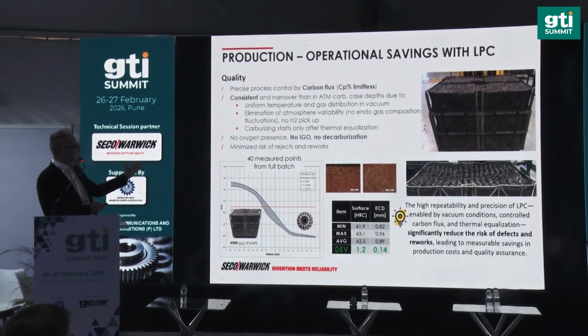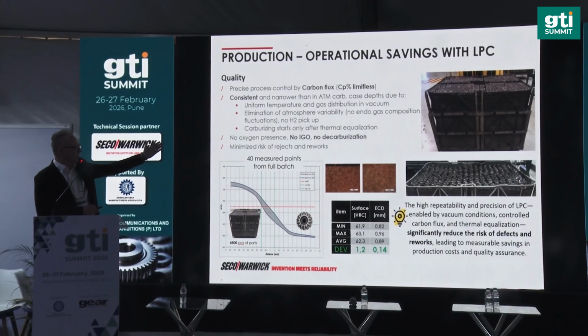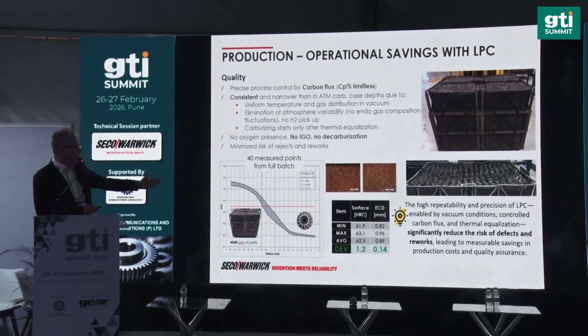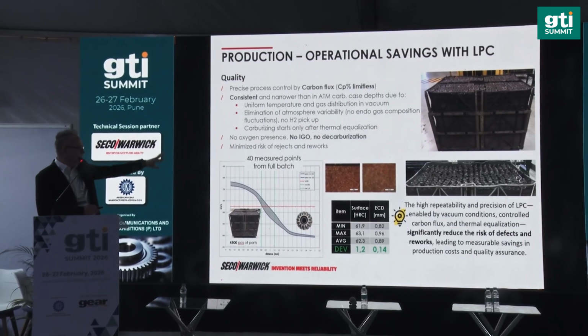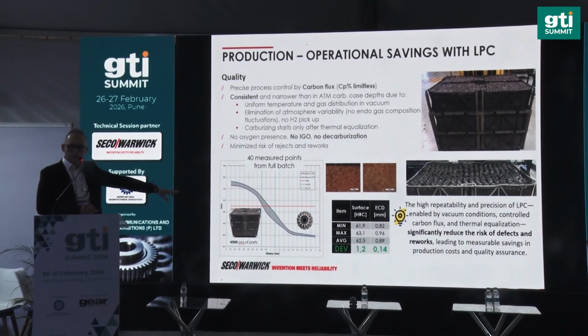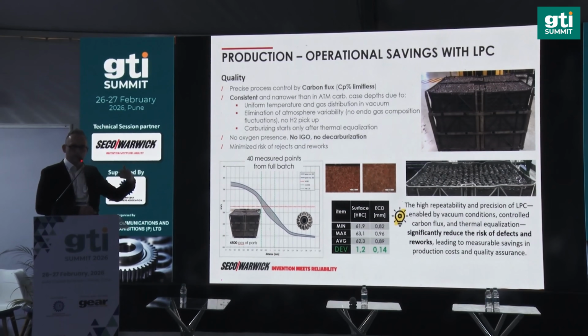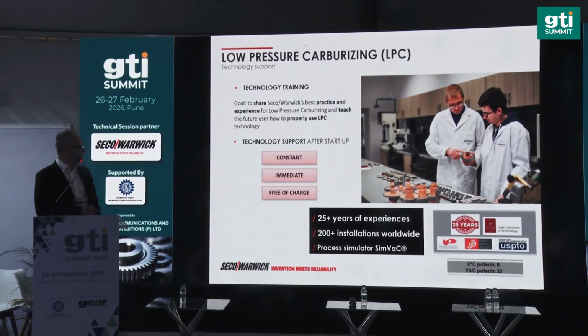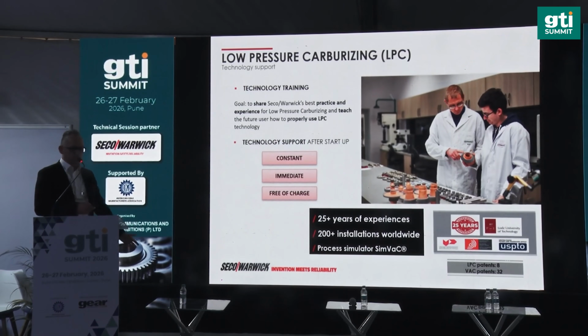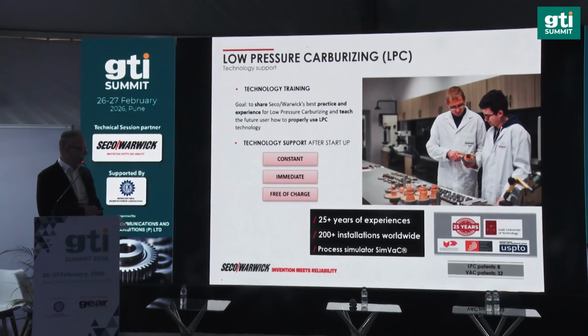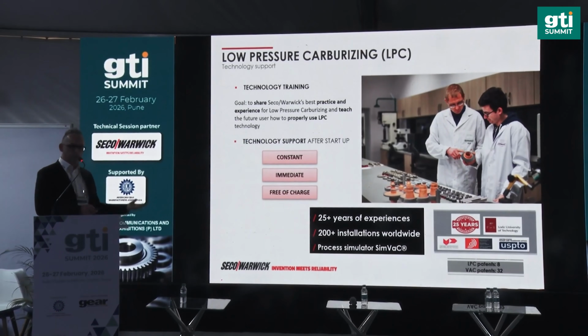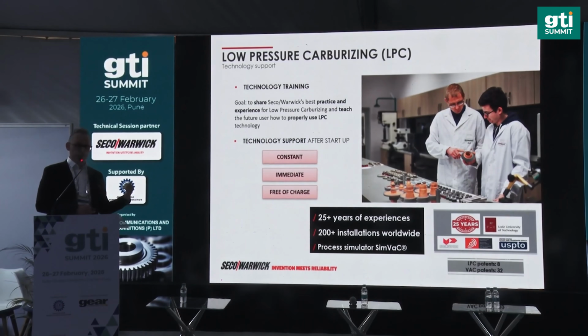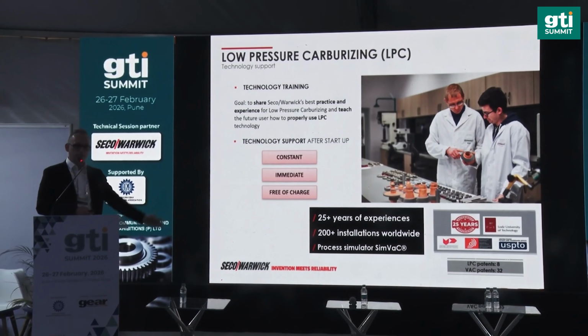Quality: just imagine 4,500 side gear parts densely packed in such a load, and after processing, measured on 40 parts within the whole batch, you got a tolerance of 0.14 mm spread of the case depth. That means the quality is at the very highest level. And what we can also share is that we've got more than 25 years of experience running LPC carburizing installations, more than 200 installations all over the world. But also we share the knowledge by utilizing our equipment and our R&D. And again, I can confirm that R&D testing labs are the right direction for the development of any aspect, as was already said at the beginning in the first session.